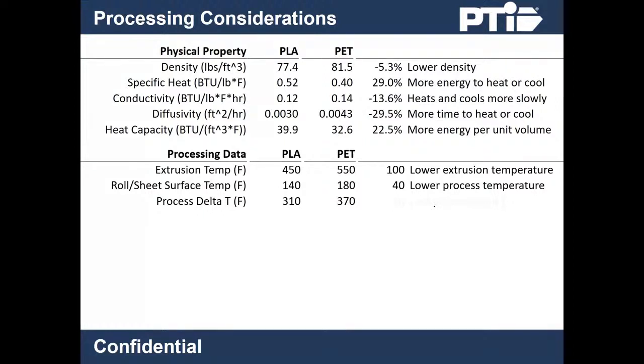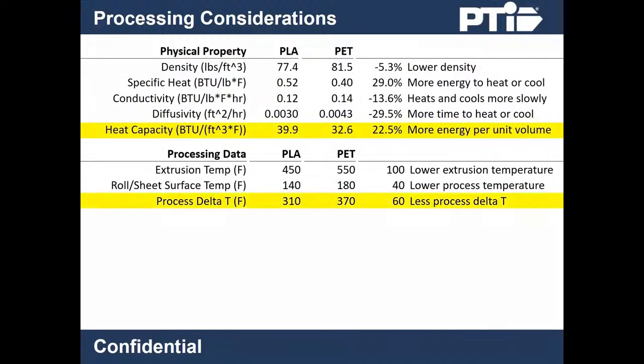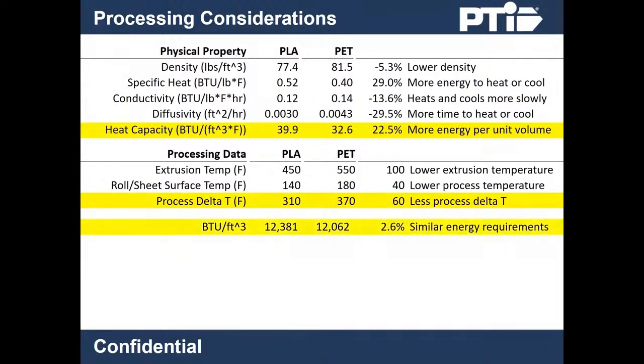The process delta T is calculated by subtracting the sheet surface temperature from the extrusion temperature. PLA is less than PET, which sounds favorable, but we have more work to do. When we calculate actual heat load, which is the volumetric heat capacity times the process delta T, we see that PLA has a slightly higher heat load, even with the lower process delta T. But it gets worse. Most sheet processors don't consider volume, they consider mass.